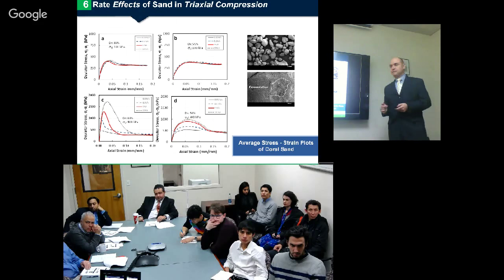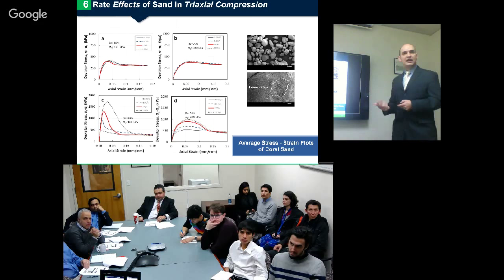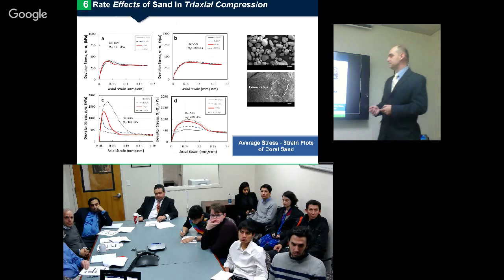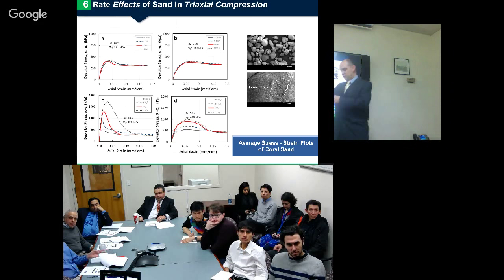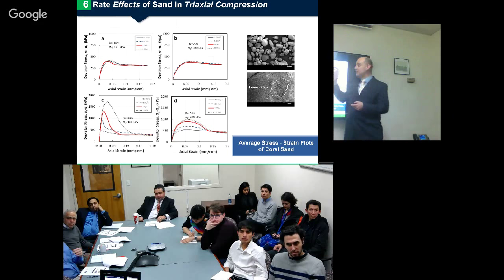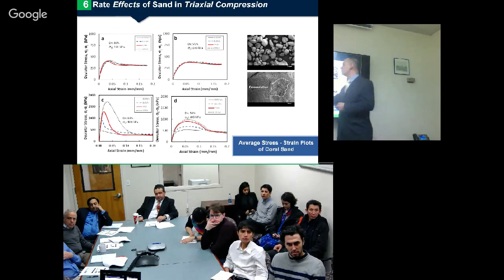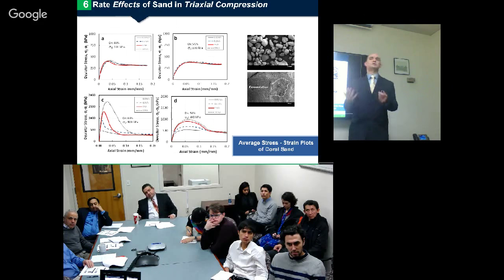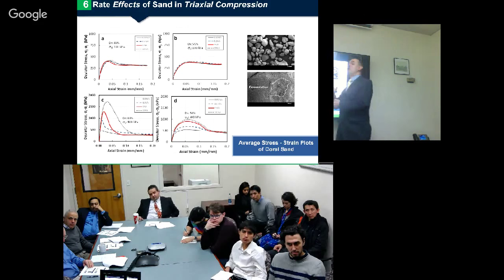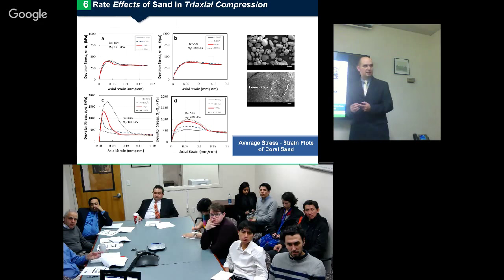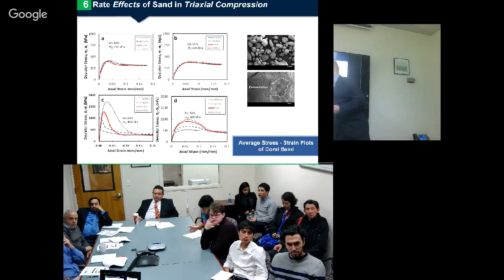On the other side, we have a coral sand of calcareous material, and we have these two conditions. We saw these two density conditions: dense material, loose material. I only got here 100 and 400 kPa, and in 100 kPa of confinement, again, nothing in terms of strain rate dependency is seen, but here it's different.